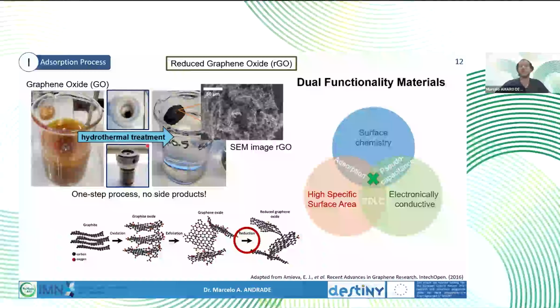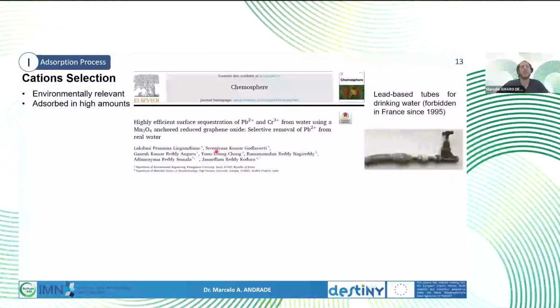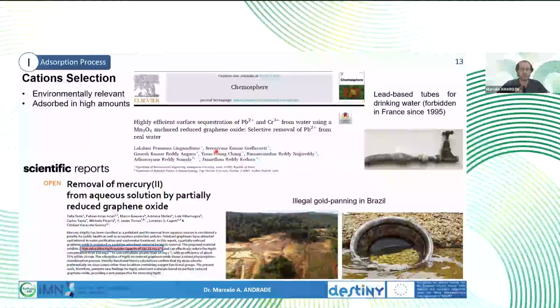And we chose a hydrothermal treatment to make these foams. So they ended up presenting a high surface area and a very easy synthesis process. Having selected the adsorbents, we needed to select the cation to study. There are several cations that are environmentally relevant and that can be adsorbed in high amounts, so we would be able to test, such as lead, chromium, and mercury.